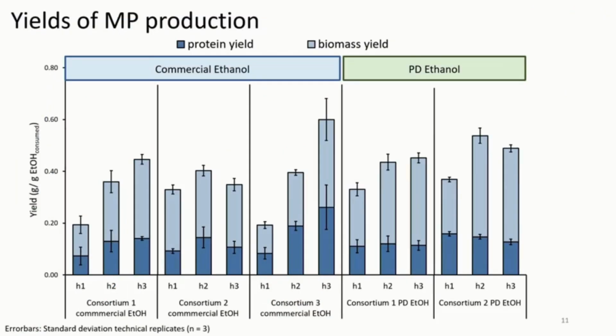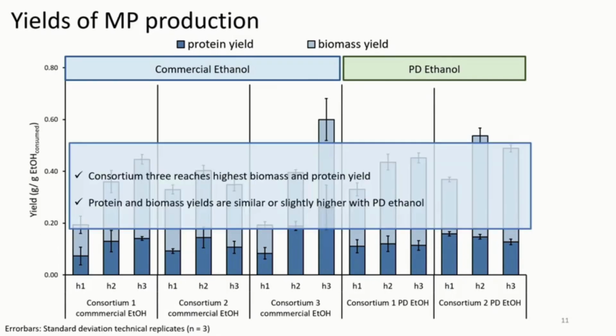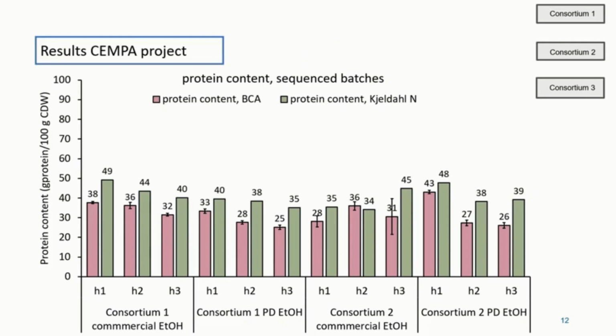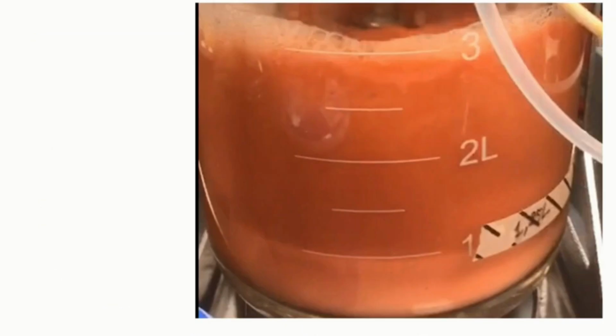It comes at quite a nice growth yield, up to 60% of the substrate ending up in the product, both for commercial sources and the pre-distilled ethanol. And it has a nice, appreciable protein content. But what's also interesting, this is a photo of these microorganisms, and they don't look like how you typically think about growing microorganisms. You were probably expecting something white. These are bright red. So we have selected microorganisms that not only grow really well on ethanol, they also produce other colorful products like carotenoids.